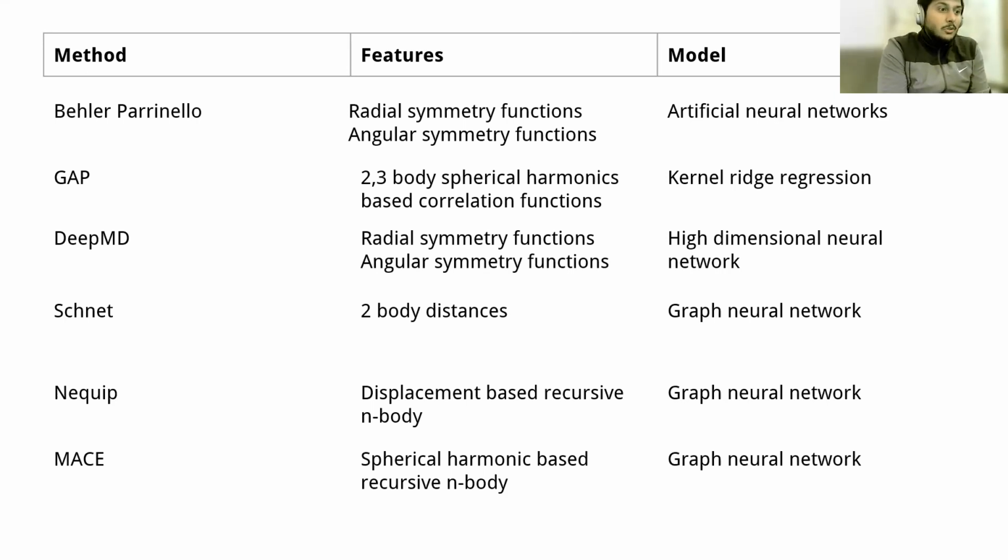And that is why you need to use an architecture which respects these symmetries, which is equivariant to these symmetries, which means that it can be both invariant. So you can construct terms which will not change if you make some sort of changes along a particular symmetry group. But then you can also construct abstract quantities which will also rotate in the same way or have exactly the same symmetries as your input, right?